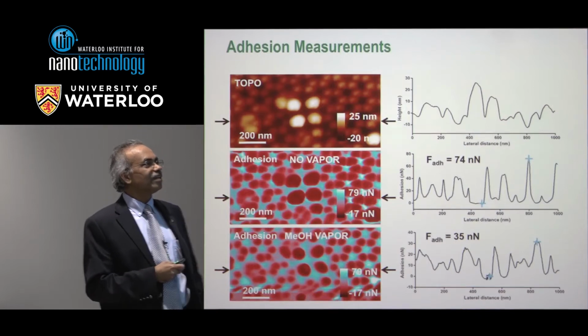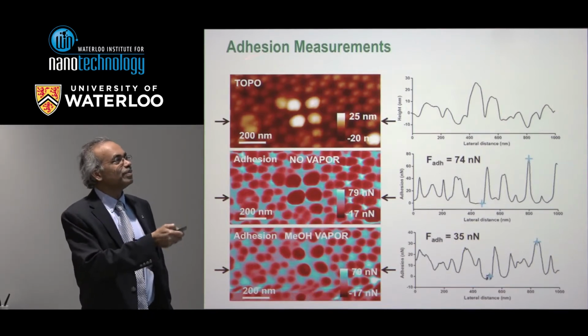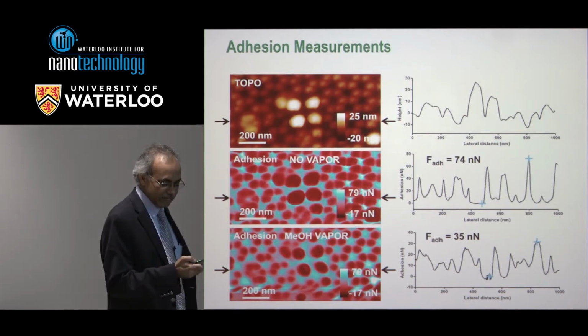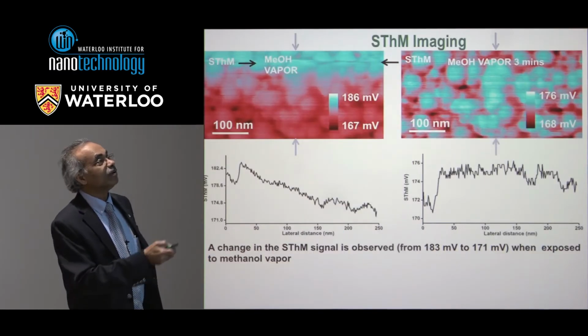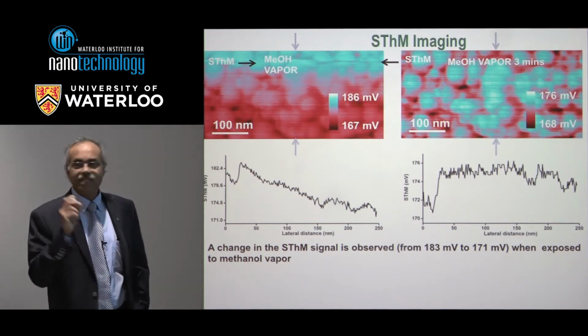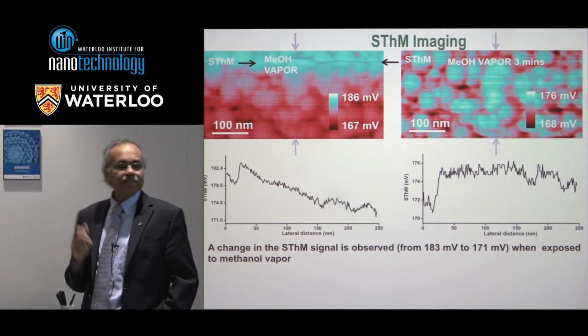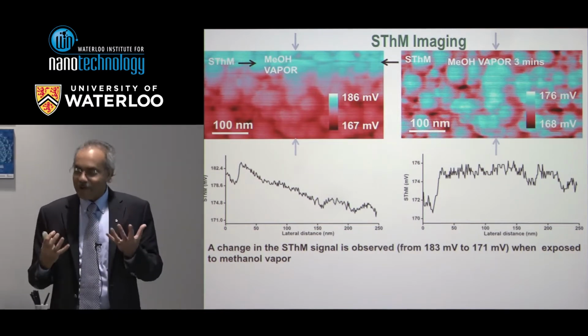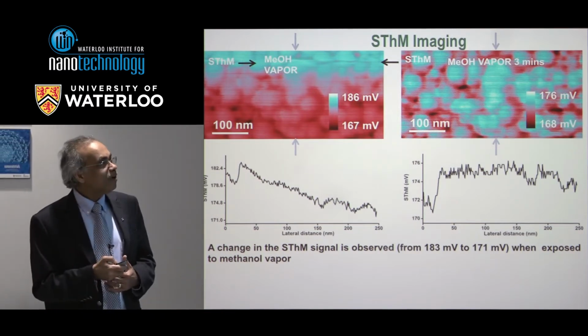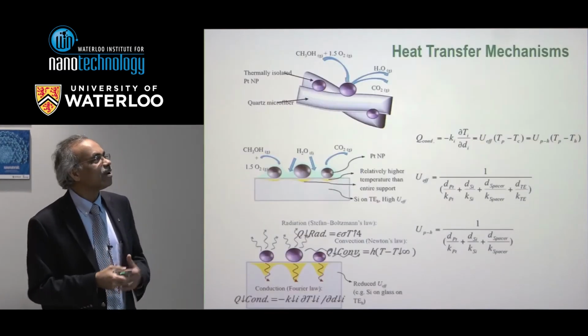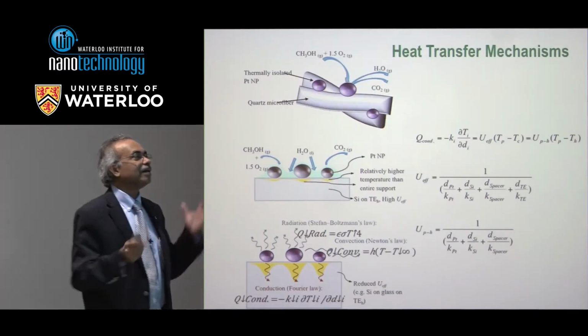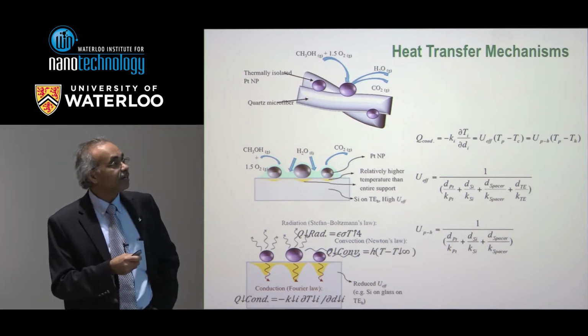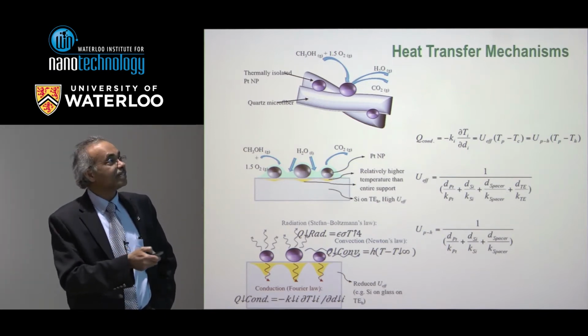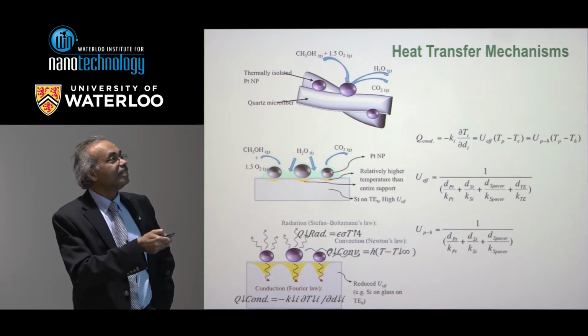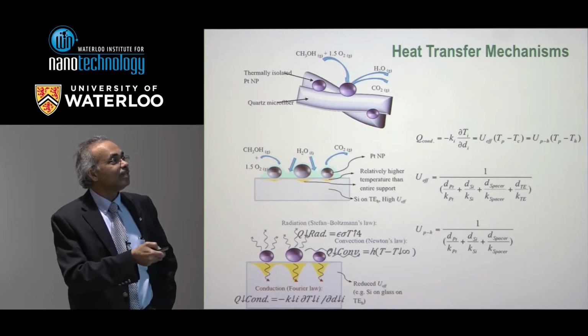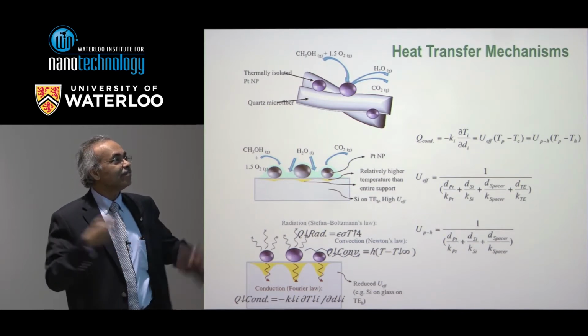So we started looking at the adhesion measurement with the AFM. These are nanoparticles. We can look at the heat with a scanning thermal microscope, and we can see that they are very hot particles. But how come we cannot get any power out of this thing? So what we realized is that there are a couple of different ways heat is being generated and then transmitted across by conduction, convection, and radiation. And these are the nanoparticles on a glass wool.